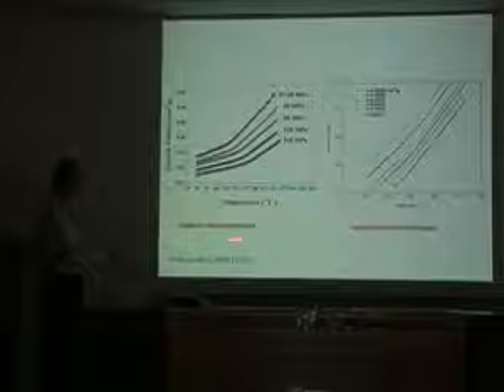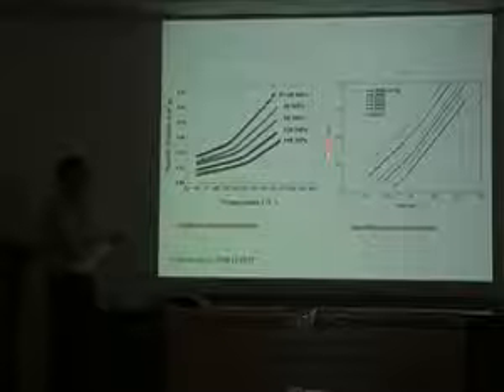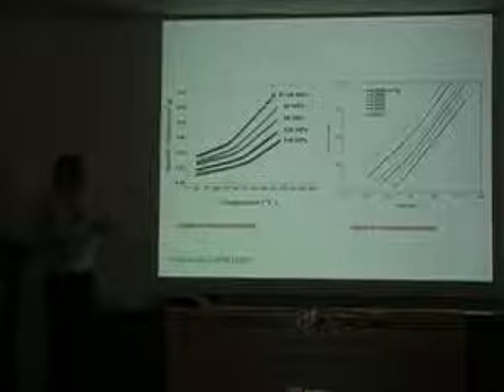Another example is, we can make a glass from specific volume temperature experiments, these isobaric measurements. This is a polycarbonate glass, and we see the typical behavior that the TG is a function of pressure. Now, here, it's harder to see. These are isochoric measurements. So we can form a glass by changing pressure as a function of temperature, but at constant volume. And these are constant volume lines. You can see here that the strength of the transition is not as strong as in this case. But I'm just showing that, in fact, the behavior, obviously, this glassy surface is different from this glassy surface.